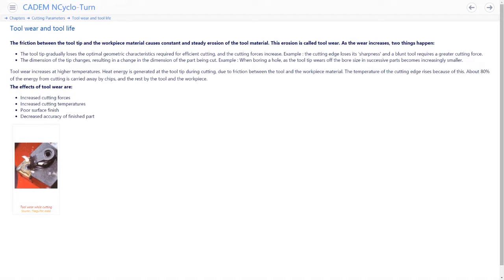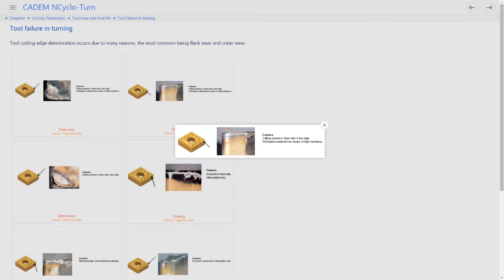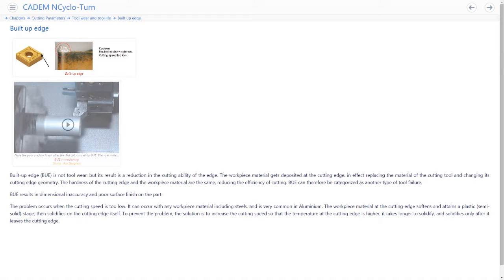Tool wear is the erosion of material from the tool. It changes the shape of the tool cutting edge, increases cutting forces, and results in poorer accuracy and surface finish on the part. These are some types of tool wear. Flank wear is the most common — it makes the cutting edge more blunt, resulting in higher cutting forces and changes in part dimensions. Built-up edge is the deposition of work piece material on the cutting edge of the tool. It is not actually tool wear, but its effects are the same. The deposited work piece material becomes the cutting edge, so cutting forces become high and dimensional accuracy and surface finish are poor.